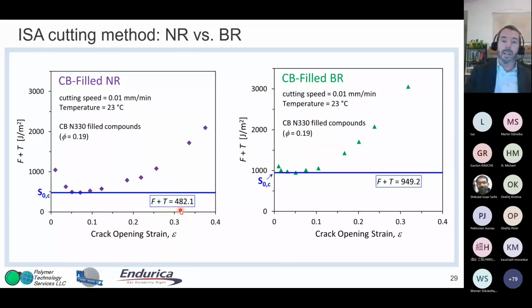Remember, this is at the other end of the crack growth curve. And you can now already see that there's going to be a flip of behavior. Now, butadiene rubber is showing much better crack growth resistance.